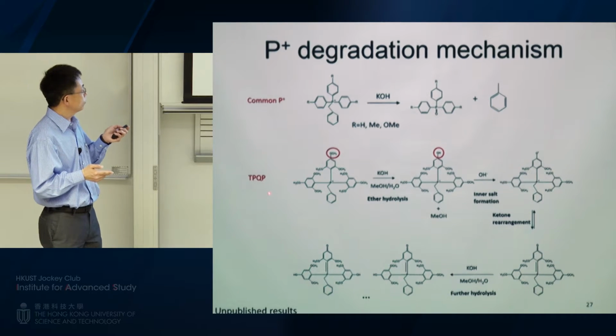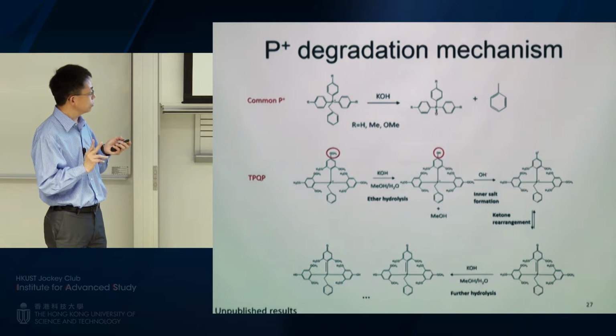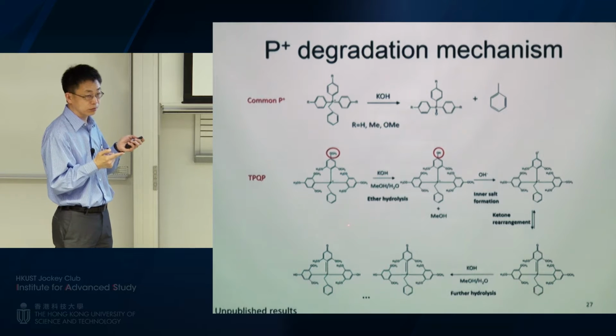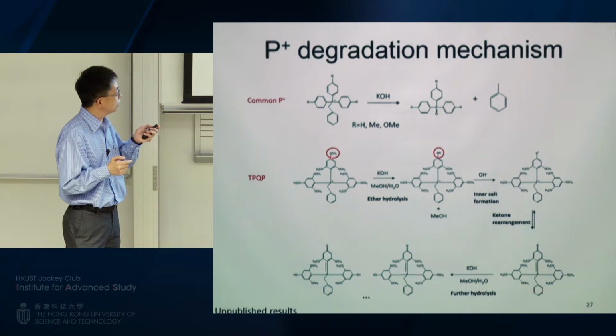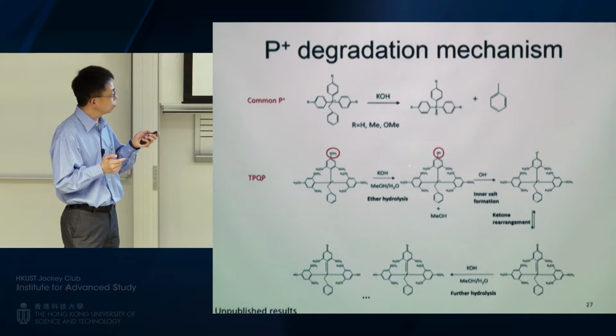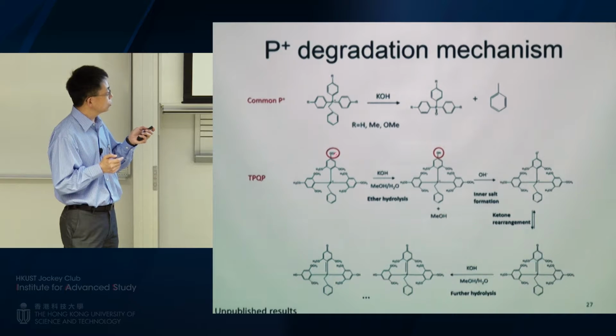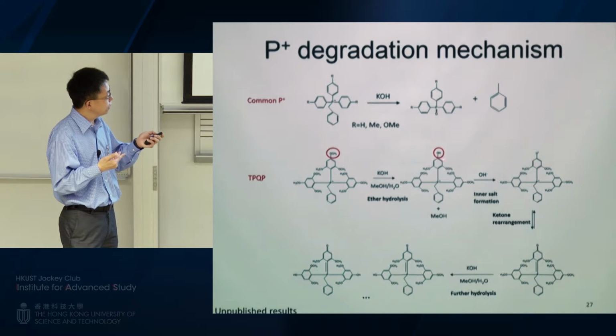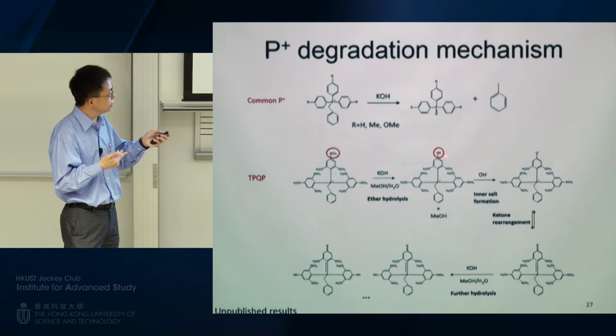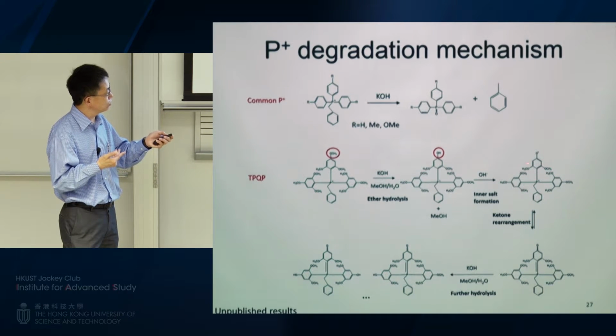What we found was, for the 9-methoxy one, it goes through a totally different mechanism. This is a little bit small, especially for people in the back, so imagine here with me, this is the methoxy group. The first step is actually hydrolysis. When you have this KOH here, you turn this methoxy group into a hydroxyl group. And then the next step is deprotonation. You take the proton away, you form an O- here, and you have a P+ here, and this is a conjugated system. So you can have this ketone rearrangement. You form a double bond here, and then you take away the positive charge as well as the negative charge.